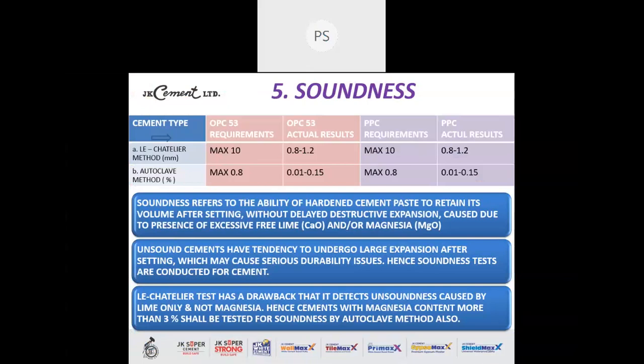The OPC 53 actual results in India are between 0.8 to 1.2 mm and 0.01 to 0.15% respectively. Now the PPC requirements as per IS code are the same, maximum 10 mm and maximum 0.8% respectively. We get actual result range of 0.8 to 1.2 mm and 0.01 to 0.15% respectively.